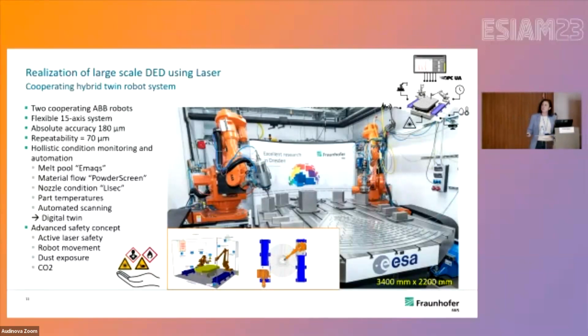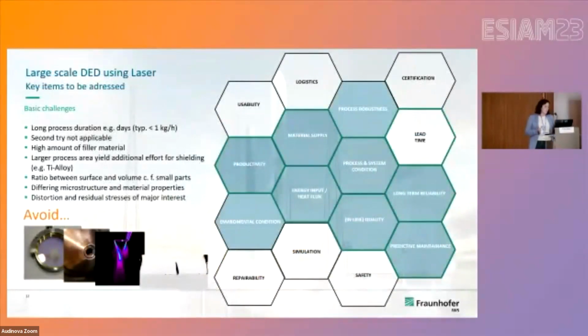A huge issue as we are working in an open atmosphere is obviously laser safety and also particle safety. So we also developed the so-called powder screen measurement system to measure particles in suspension in the lab to assure that the co-workers were not affected by these things. So a couple of things you need to take into consideration. It's a huge headache, obviously, to print such a huge part. We are talking about 1.5 meters for the first prototype. So all of these things need to be taken into consideration.